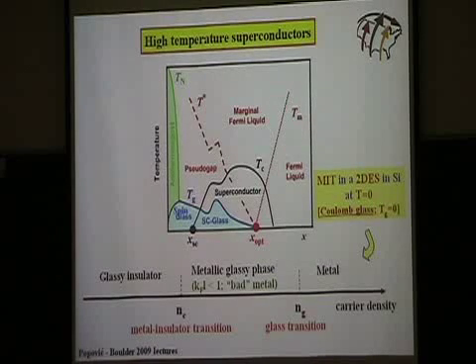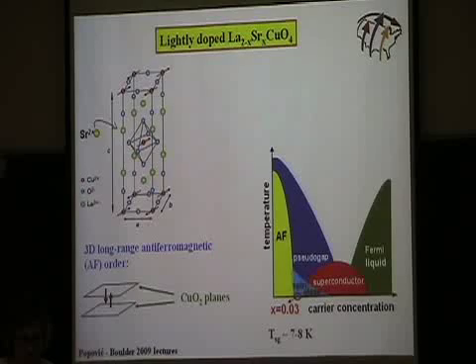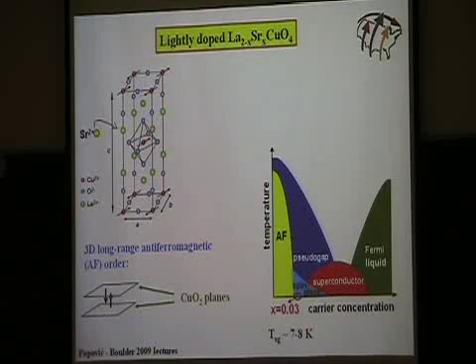So in other words, we want to see if there is some kind of universal behavior. So what we wanted to do is basically look at the ground state and then see whether at low doping we have a glassy insulator, and then if we do, to see how this evolves as a function of doping. So the material that we selected is this lanthanum cuprate, which has these planes of copper and oxygen atoms where all the action takes place, and usually it's doped with strontium, which substitutes these lanthanum atoms.